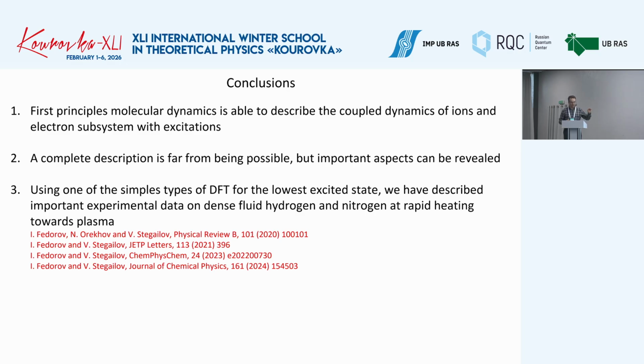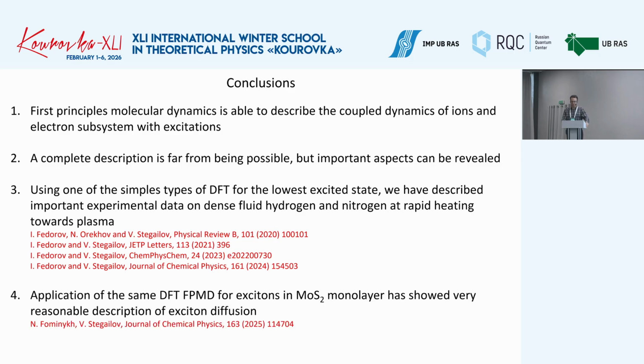At quite simple DFT level, this approach allowed us to obtain very nice correspondence with experimental data for dense fluids, hydrogen and nitrogen, and our first results for molybdenum S2 monolayer are also encouraging. Thank you.